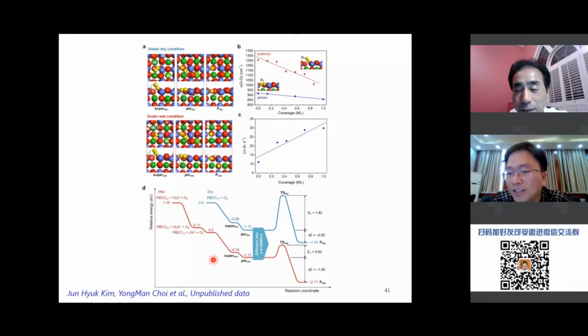Yes, absolutely. Vacancy is critical. Oxygen vacancy is critical for all those processes. Now, cerium oxide is well known to be very flexible with oxygen, so you can easily create oxygen vacancies. And if there's oxygen in the atmosphere, cerium oxide can take up oxygen or release oxygen readily. That's one of the unique properties of cerium oxide, and that's why it's so efficient. Silver oxide is actually used in a lot of catalysts, like the three-way NOx removal catalyst. So cerium oxide is well known to create a lot of vacancies. When you introduce other elements like nickel, ruthenium, that will create additional vacancies.